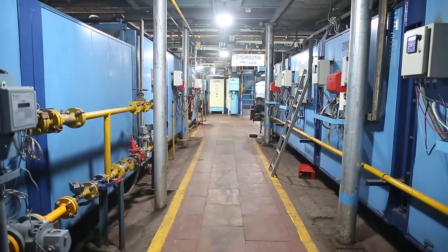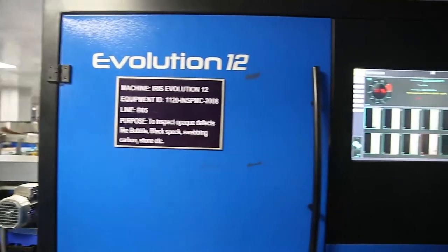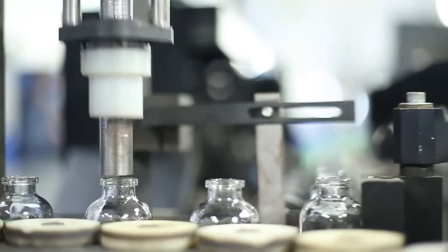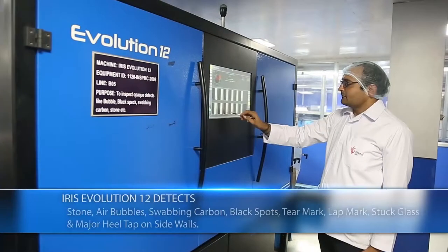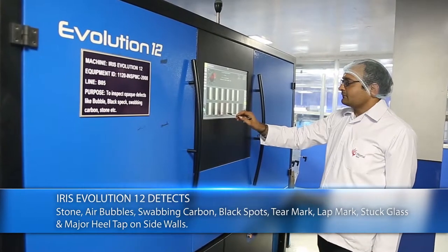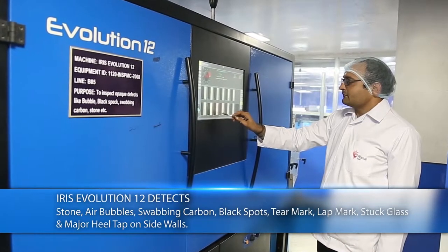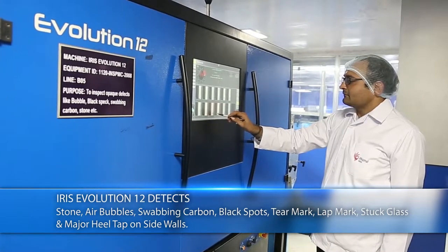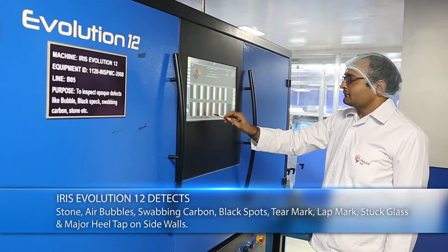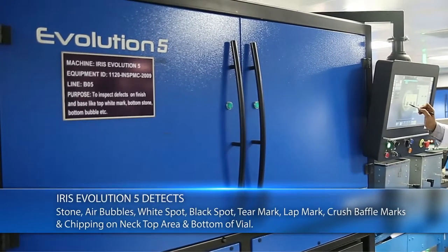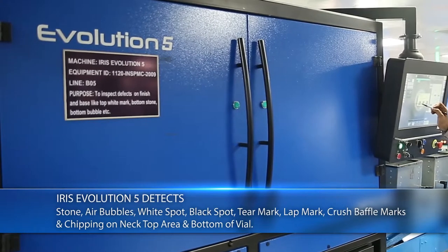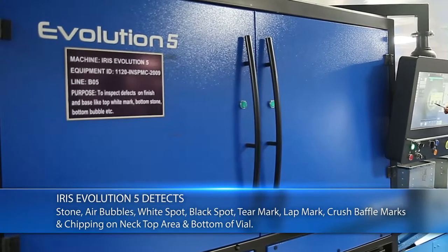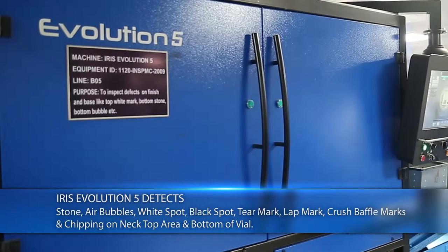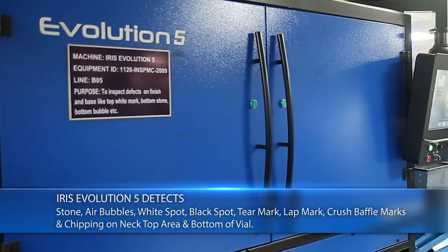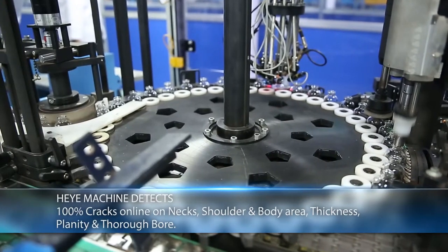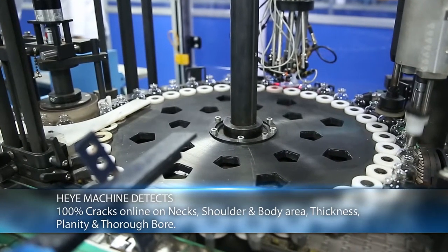Piramal Glass facilities house auto inspection machines: Iris Evolution 12, Iris Evolution 5, and Heye machine. While Iris Evolution 12 detects defects like stone, air bubbles, swabbing carbon, black spots, tear mark, lap mark, stuck glass and major heel tap on side walls, Iris Evolution 5 detects defects like stone, air bubbles, white spot, black spots, tear mark, lap mark, crush baffle marks and chipping on neck top area and bottom of vial, and Heye machine to detect 100% cracks online on neck, shoulder and body areas.